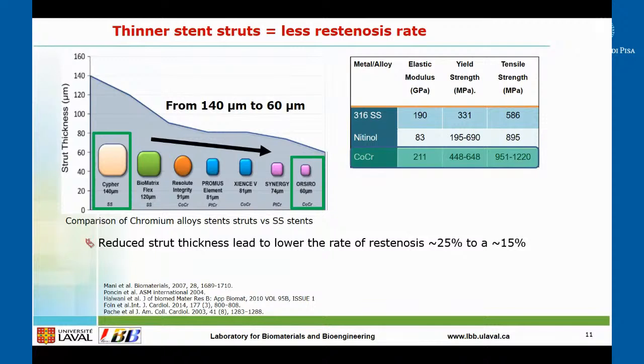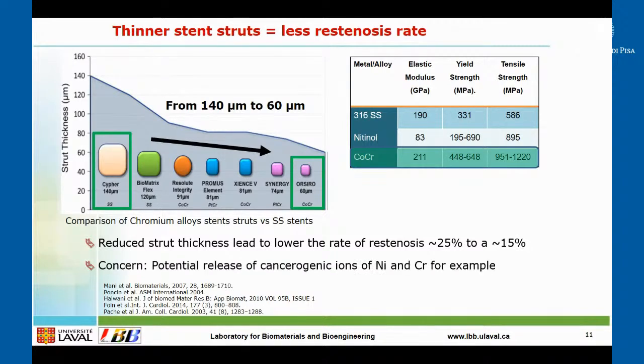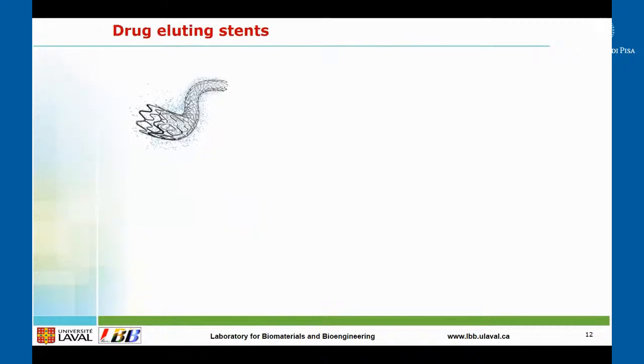However, even with a reduced strut thickness, the restenosis rate decreased only from 25 to 15%. So this means that one stent out of 6 or 7 still has a problem. There is also the potential release of carcinogenic ions, nickel and chromium. Chrome cobalt is an alloy with 30 to 40% of chromium.